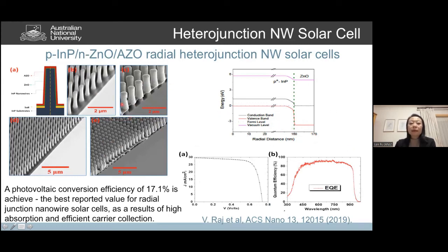And we also designed the nanowire array to have very high absorption, so we can achieve very high quantum efficiency in the nanowire. We demonstrated 17% efficiency, which I think is the best reported value for radial junction nanowire solar cells.